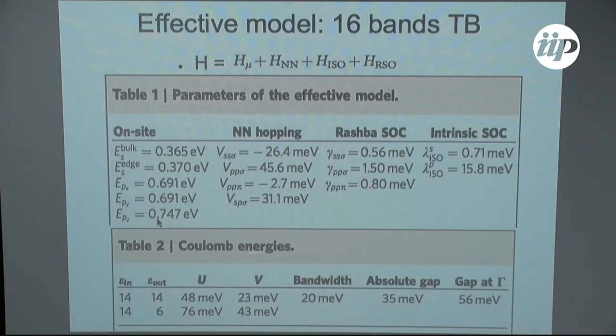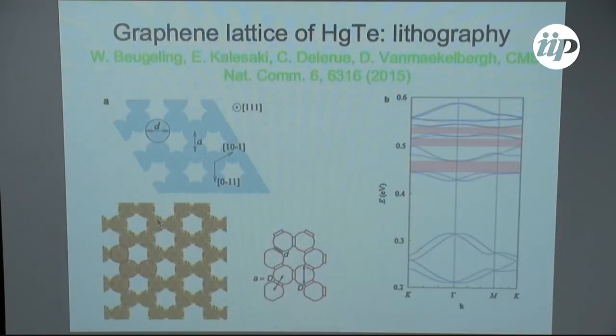So we have also been estimating the on-site Hubbard U and nearest neighbor interactions, and they are very large. So it's a very nice material where you could realize the quantum spin Hall effect at room temperatures. Of course, you don't need to use just these nanocrystals that we have been using.